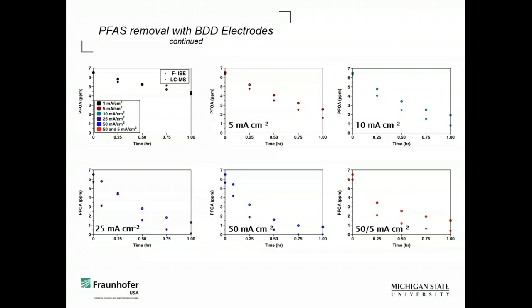And so we thought that even though our LCMS measurement is only going to give us the PFOA, if we reference that against our fluoride measurements, we know that we're probably generating short chains. Because if we don't get all the fluoride back, we know we still have complex fluoride, but the LCMS will tell us actually where the PFOA is at.